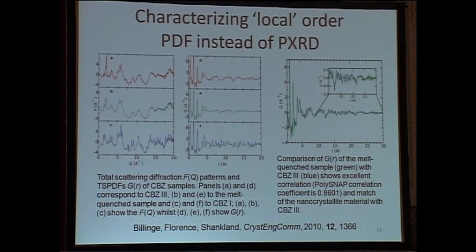Of course, as I said, a thorough characterization of these eutectics is still pending in our lab, and the way to go perhaps would be to go to the high energy synchrotron sources. We heard about the developments and the future in this area in yesterday evening's lecture. So the idea would be to not look at the intensity versus the 2 theta plot, but to look at the radial distribution functions. And this is where, at the short range of 8 to 10 angstroms, one can see some of the differences.